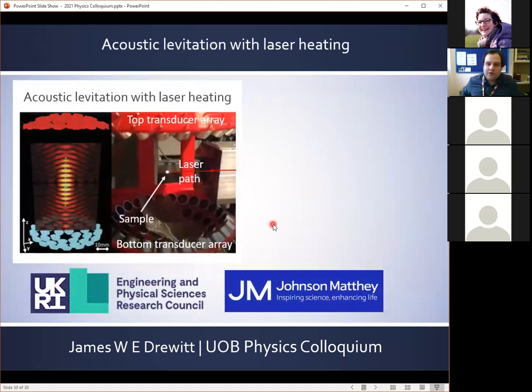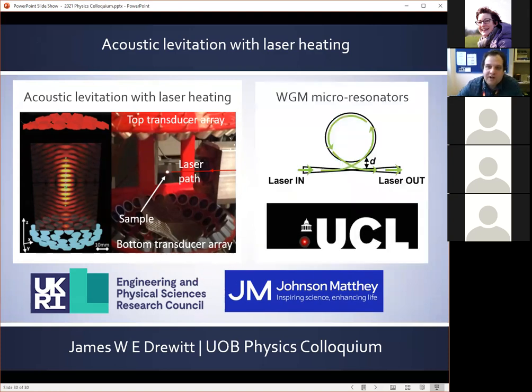And then finally, the current project which we're working on, funded by the Engineering and Physical Sciences Research Council here in physics, is to develop the technique of acoustic levitation with laser heating in order to fabricate novel glass compositions. And in fact, using acoustic levitation instead of aerodynamic levitation means that we can use smaller sample sizes and potentially have ultra fast quench rates, and so develop glass compositions which cannot be formed using any other method. And also the small scale of the glass formed this way means we can form microspheres which would have application for whispering gallery mode micro resonators, which our project partners at UCL are interested in.